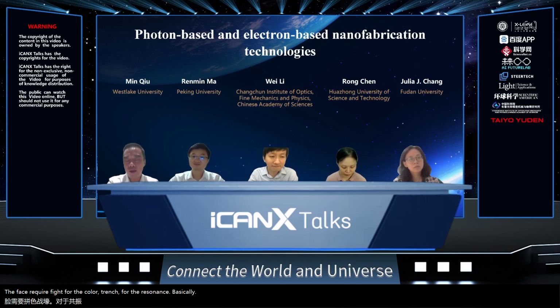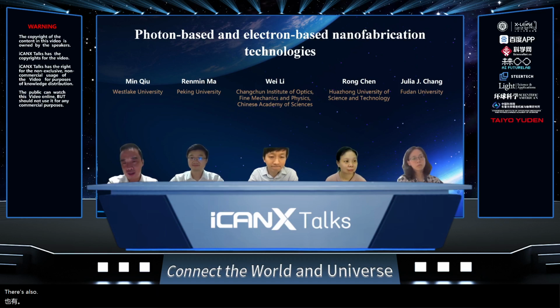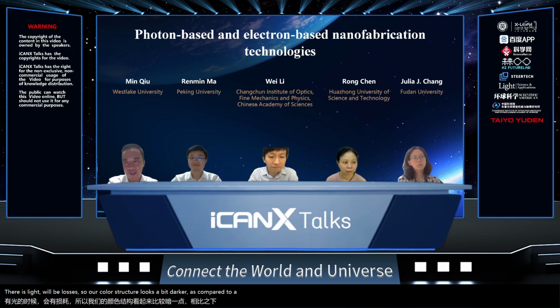But we use a very thin layer of the films. And if the layer is thin enough, it will be angle independent because the phase is coming from the absorption instead of propagation. There's also a shortcoming, a disadvantage coming out of these films: light will be lossy. So our colored structure looks a little bit darker as compared to other printed devices. So we are working on this.